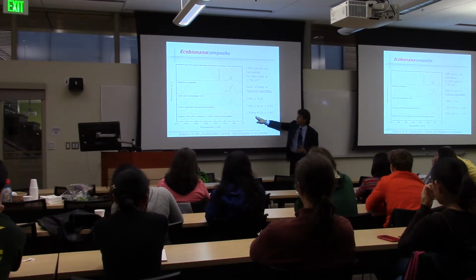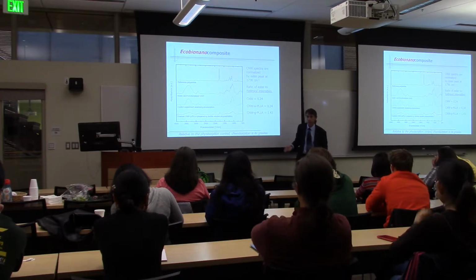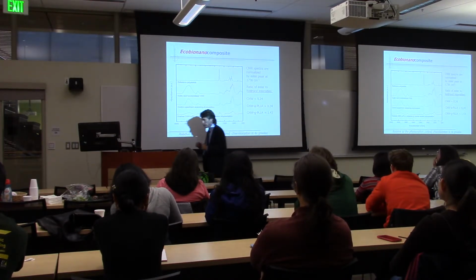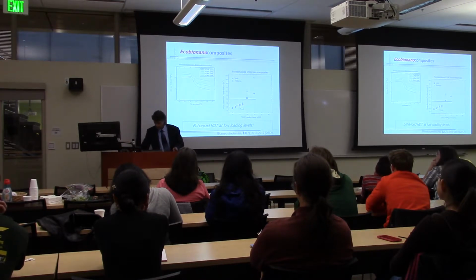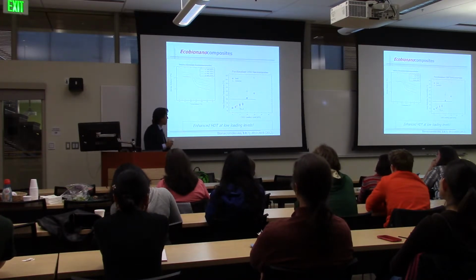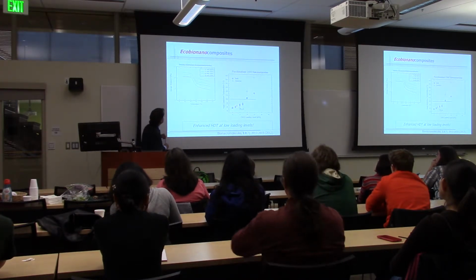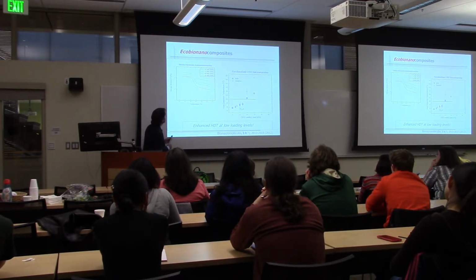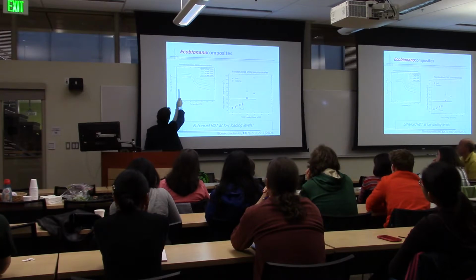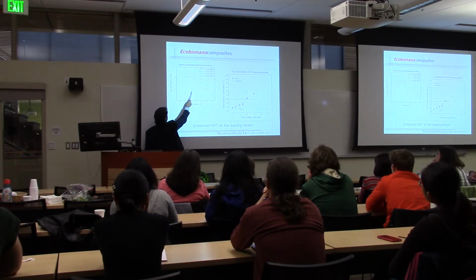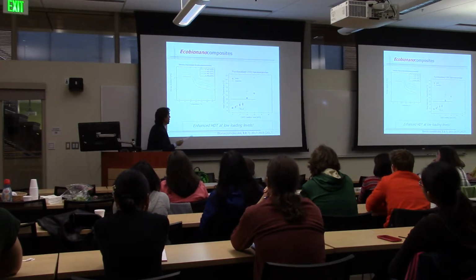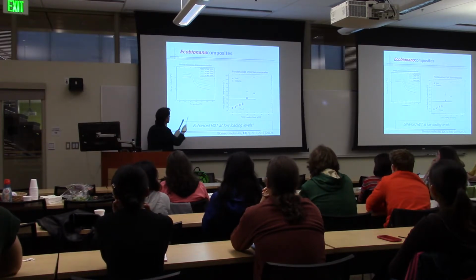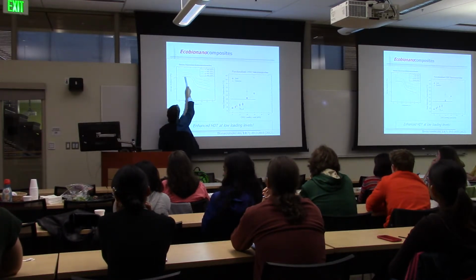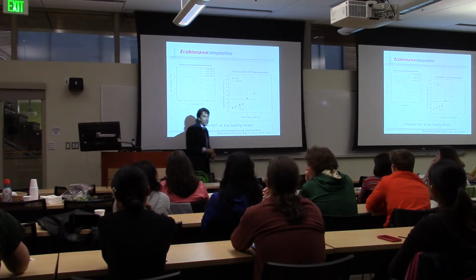However, if you then look at our grafted materials, it's 4 times larger. Okay, so there's a very profound difference. We genuinely are getting chemisorption. And of course that translates, we get very nice properties, modulus versus temperature. If we compare these, my regular PLA has a modulus on the order of 10 to the 8th at 100 degrees C. This is above that glass transition temperature. It's on the order of 10 to the 9th when you're down at room temperature, i.e. where you can use it for cold food packaging. And now if we look at filling this with my nanowhiskers, at 100 degrees C, I'm almost matching the modulus of the unfilled PLA.